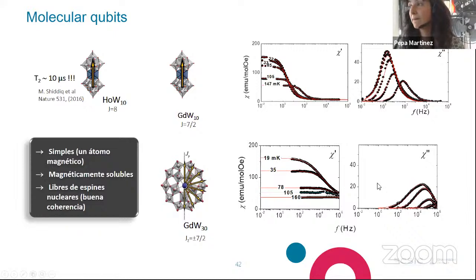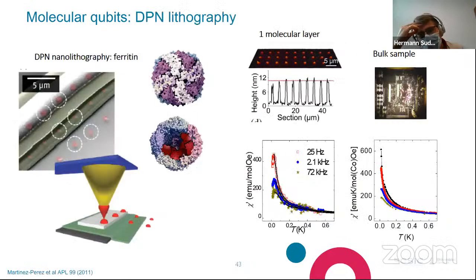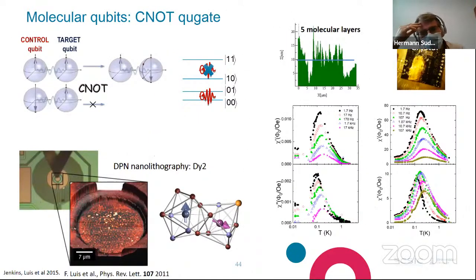Okay. And in your next example, you showed quite different curves about the susceptibility versus temperature. This one? This one, yes. Maybe it's something basic, but I did not catch why this is so different. Well, this does not tell anything in particular. You are right, because these measurements by themselves do not tell that these nice effects of the CNOT gate are indeed taking place. I show them because they show very nicely that measurements performed in a five-molecular layer and measurements performed in a crystal exhibit the same results.